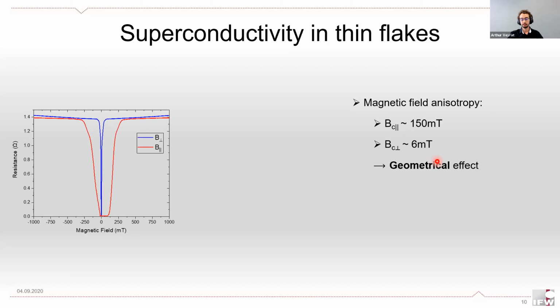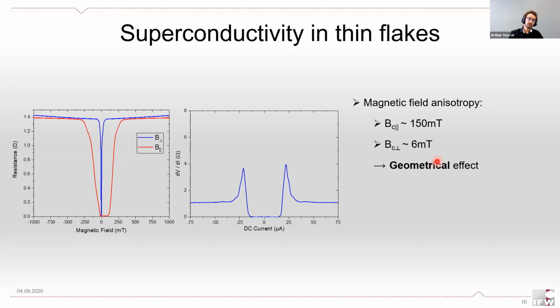So it is going to be more difficult to expel the field around the sample if the field is applied perpendicularly. We also did some differential resistance measurements, so dV over dI, shown here versus DC current. At low current, we have the typical superconducting state of zero resistance. At high current, we find a normal resistance state. And in the middle, we have these differential resistance peaks.